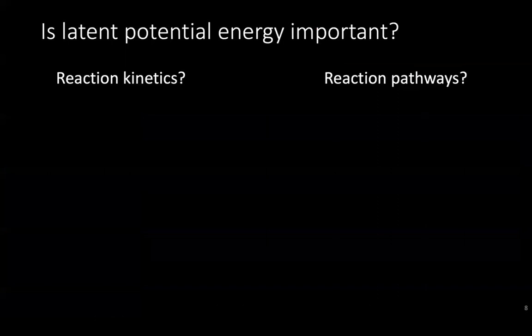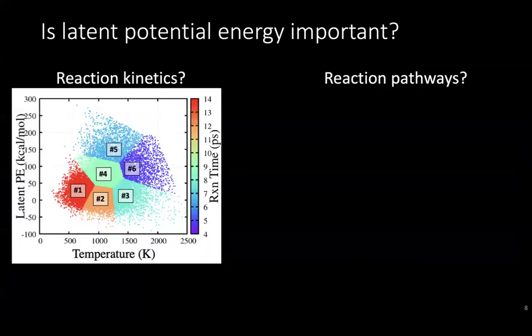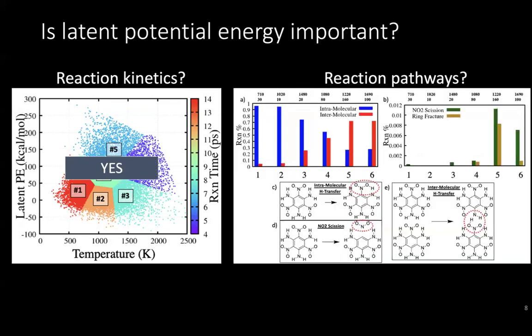So we ask ourselves, is this important? Is the fact that these molecules are twisted out of shape important for kinetics? And the answer is yes. This latent potential energy accelerates the reaction, so you can be at the same temperature, but a highly distorted mode. This is not a weird, extremely hard to understand concept, right? You're starting from a higher potential energy state, so you're going to react faster. Your reagent is excited. And so it does affect the kinetics. That's what we were trying to explain, but it also affects the chemical reactions. And so the way you decompose as a molecule, which bond breaks first and what proton transfer occurs first, is actually affected by this molecular strain, okay?